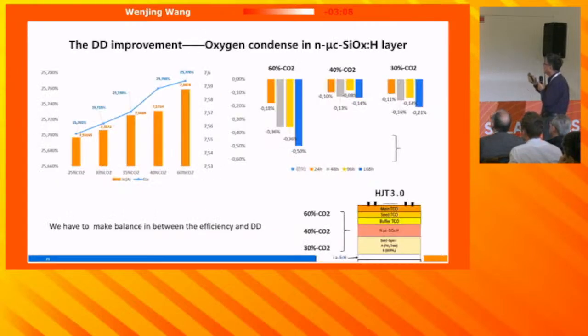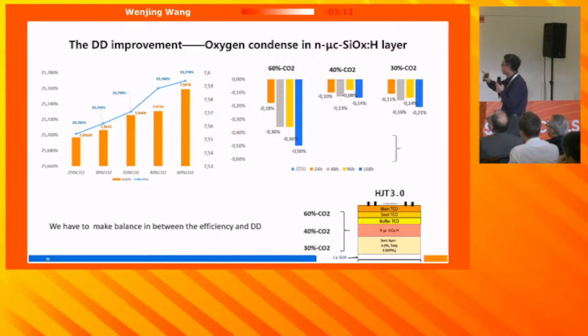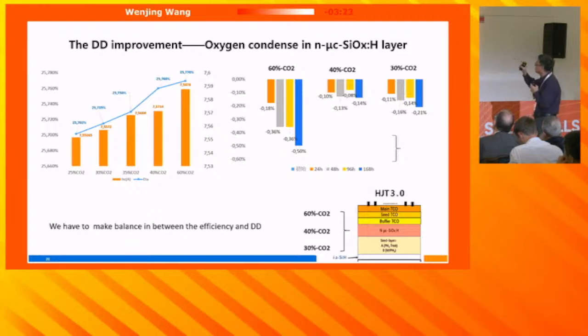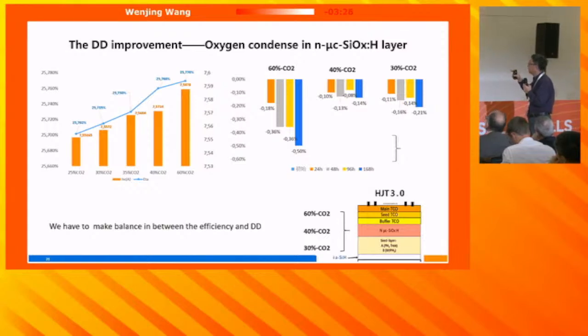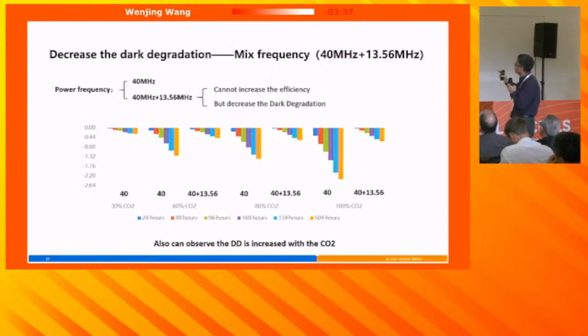So for dark degradation, we also find a trade-off. If we want to increase the efficiency, we have to put more oxygen inside the N-type layer, the N-type microcrystalline layer. But that will cause dark degradation. So we have to make a balance between the efficiency and dark degradation. And also recently we found that a new mixed frequency technology, using 40 megahertz and 13.56 megahertz, can make the dark degradation become low. So we can use even higher oxygen content.